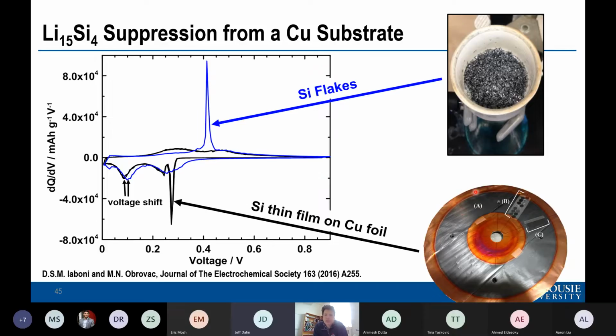And that's what we found. We could turn the 15-4 transition on and off depending if the material was on a thin film. So this is pure amorphous silicon sputtered on a copper foil. And Douglas cut the foil in half, and half of it he put in acid to dissolve the copper, and he got the flakes of silicon, and he put that in a regular coating.